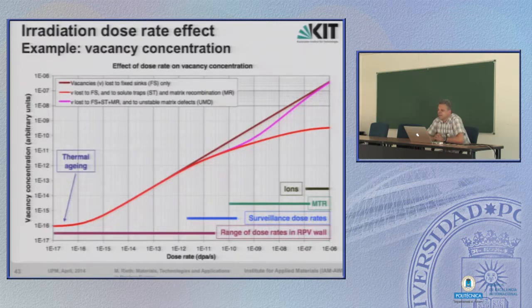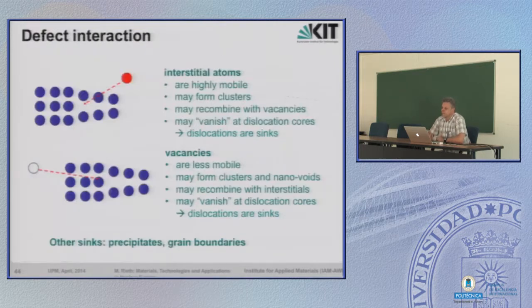And this we have to consider now more in detail. That's the defect interaction. Let's first consider interstitial atoms. They are highly mobile, as we have seen. They may form clusters, this we have seen. They may also recombine with vacancies. That's clear, because if it jumps back into a vacancy, then we have again the perfect lattice at that point. But they may also vanish at dislocation cores.